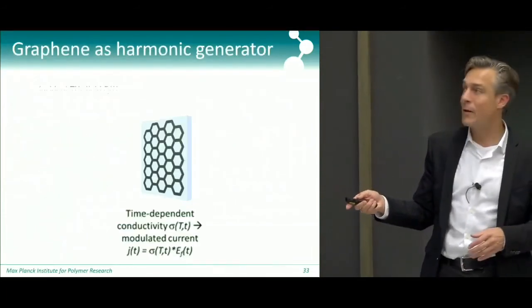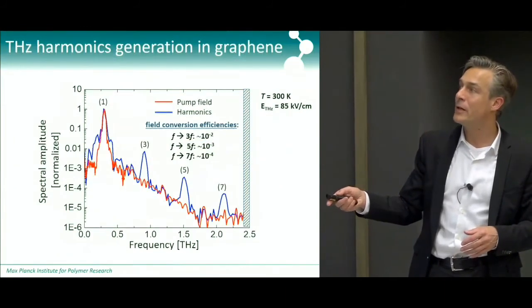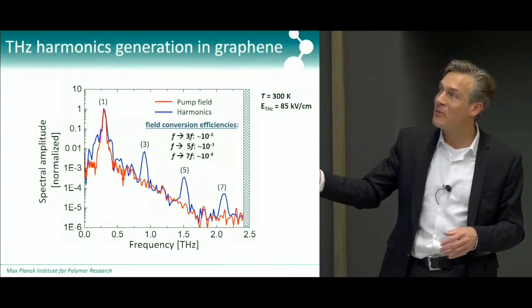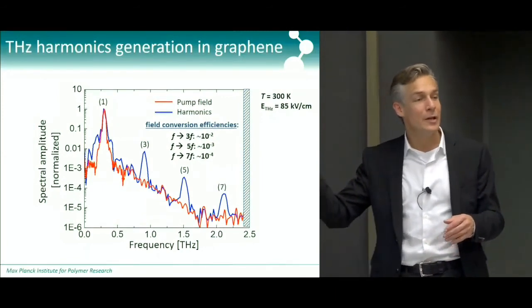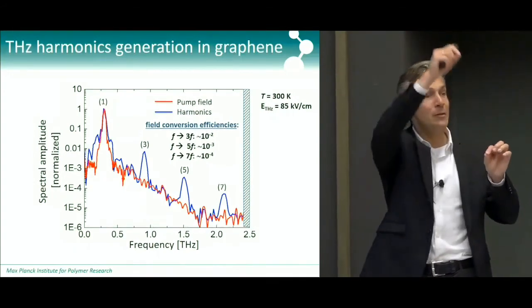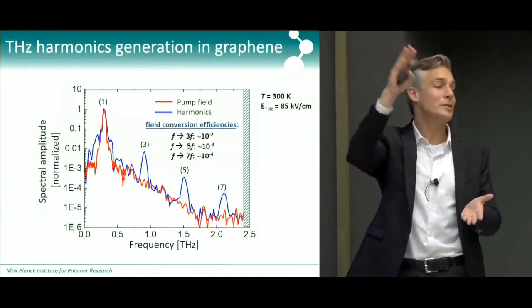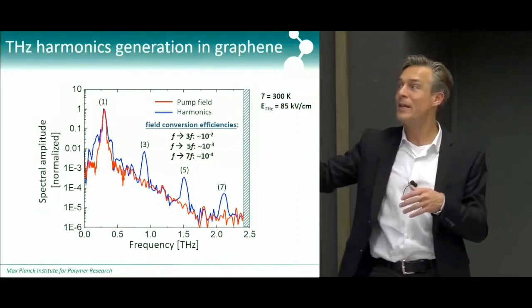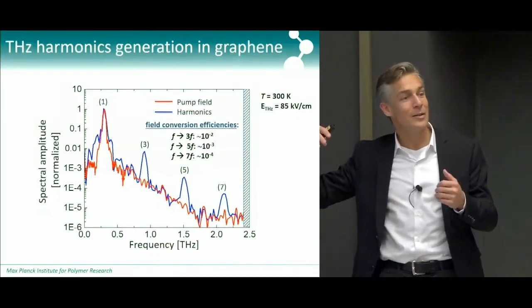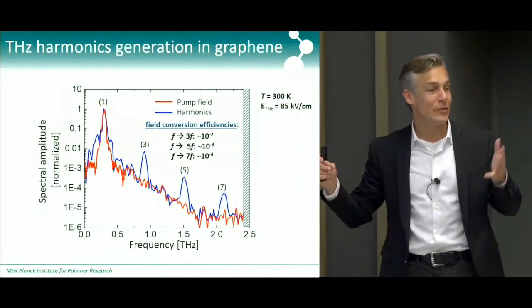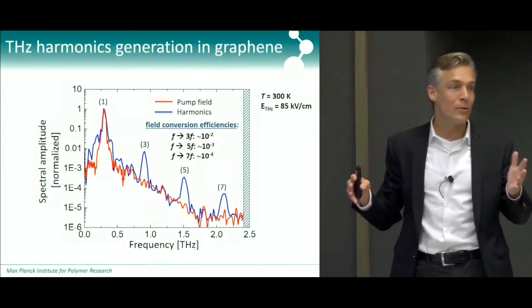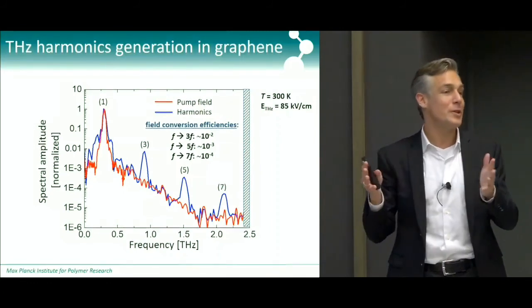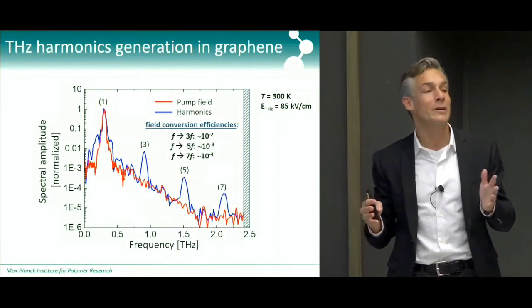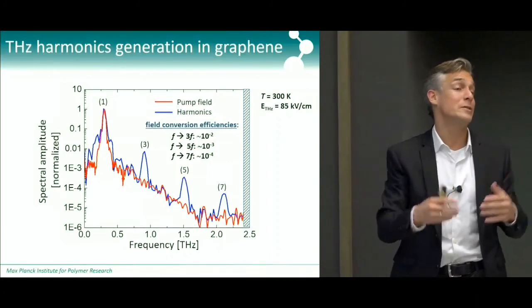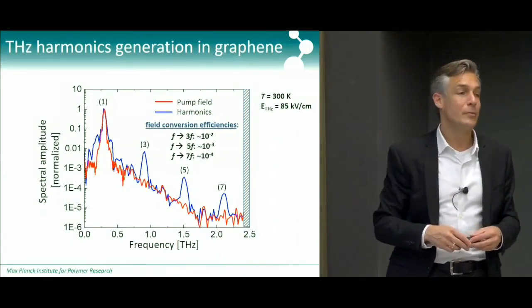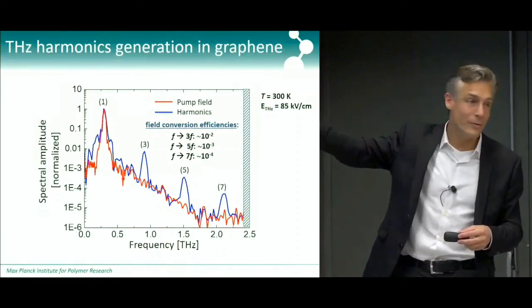It's roughly a picosecond. And if you think about this high harmonic generation, we do it at 300 gigahertz and not at higher frequencies, because at 300 gigahertz, between the peaks and valleys of the field, there's enough time for the system to cool down. And so what you would really like is to push this into the IR, but then you need faster cooling. And so we're now trying to look at how doping or sandwiching the graphene, to maybe use different cooling mechanisms, might allow us to push this into higher frequencies. So that's a very good point. That's limiting the frequencies that we can get out to.